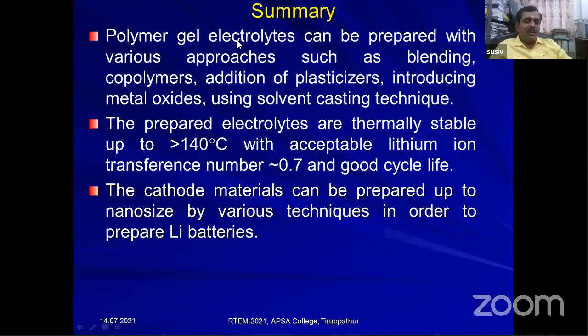I will conclude that all the polymer gel electrolytes can be prepared using various approaches by means of blending copolymers, adding a plasticizer, and introducing ceramic particles using the conventional solution casting technique. Also, the prepared electrolytes are very much thermally stable beyond 140 degrees centigrade with an acceptable transference number of 0.7 to 0.9 and a good cycle life. So based on the various preparation methods, one-dimensional, two-dimensional, and three-dimensional materials can be prepared for the fabrication of electrode materials for lithium batteries, sodium batteries, and sometimes for the 3-in-1 applications.